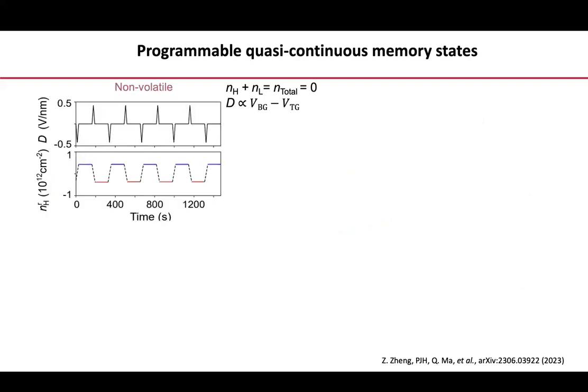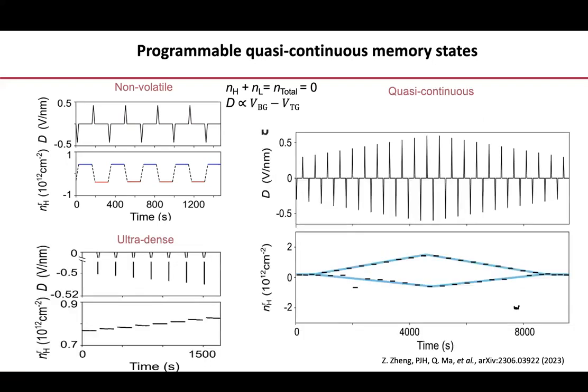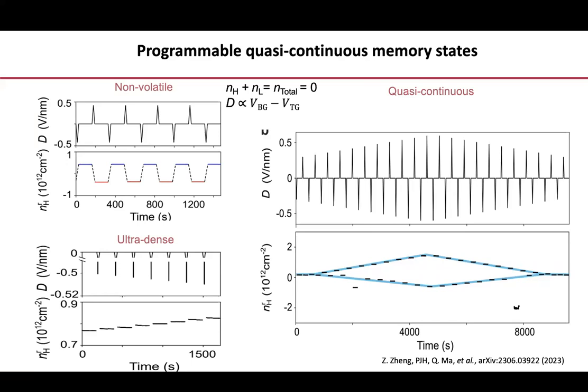In fact, we can do standard switching of these things. By the way, all of this works at room temperature. One of the few things in my lab that I've done that works at room temperature. So it can have an ultra dense memory, where you can vary continuously. You can do up to 500 states at least in the system. And I'm not showing this because my collaborators don't want me to show it, but this has certain neuromorphic computing properties which are extremely advantageous with respect to regular ferroelectrics. The system can learn much better than other systems because of the continuously tunable ferroelectric properties.